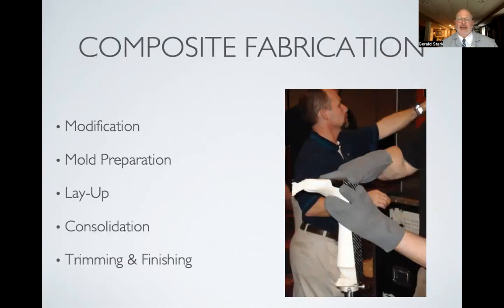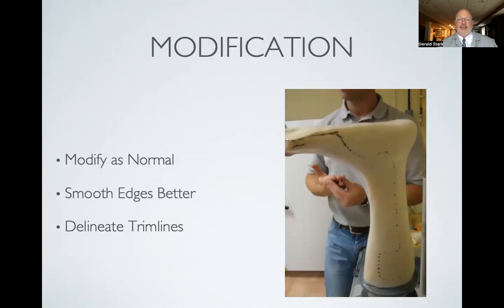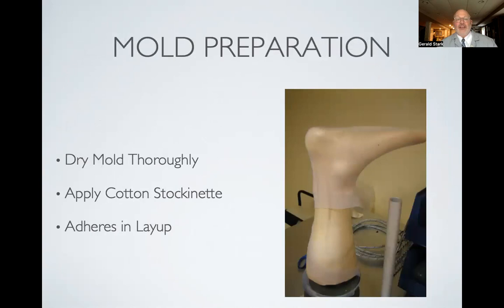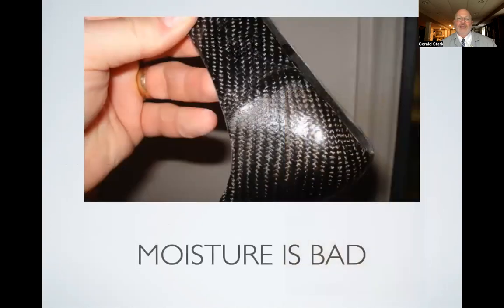And so in composite manufacture, it's really important to observe some simple rules. One is in modification. Modify as normal, but it's even more important to keep your mold, your plaster, very smooth, and to delineate these trim lines very carefully, because you're going to actually smooth them into shape. And then another thing is to really make sure that the mold is thoroughly dried, to use stockinette. Make sure that if you don't do this, then the composite will not adhere.